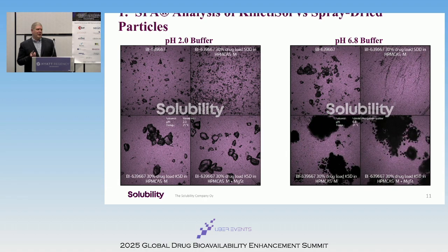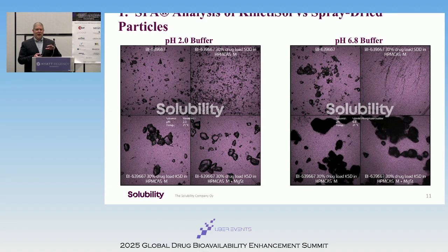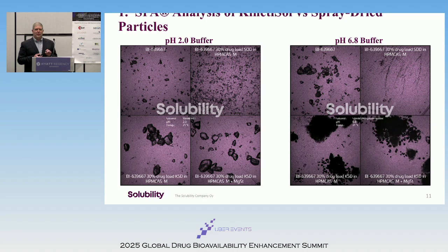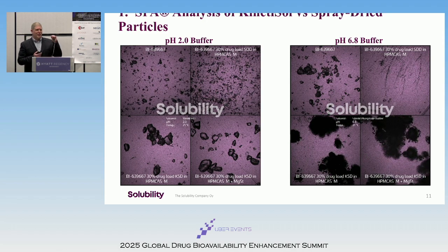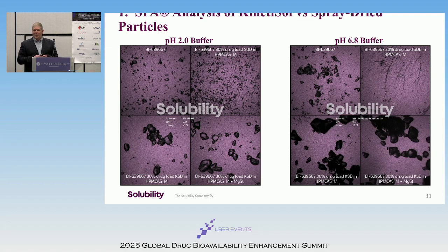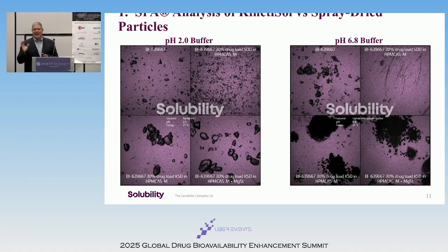And I'm going to show a few videos of what we did with the Solubility Company to basically corroborate the results and actually see what's happening. We ran the system at pH 2 and at pH 6.8. On the top row, we have the neat API and the spray-dried material. Under the pH 2 system, you could see the API slowly dissolving, so it has some solubility, but at pH 6.8, it's not dissolving at all. If you look carefully at the pH 2 buffer with the spray-dried material on the top corner, you could faintly see a little burst where there's a little bit of a dose dump. But what's really noticeable at pH 6.8, you just see a flash of material come through the video. It's quick. It takes like a second, and it dissolves. So there's your dose dumping as it transitions from pH 2 to pH 6.8.